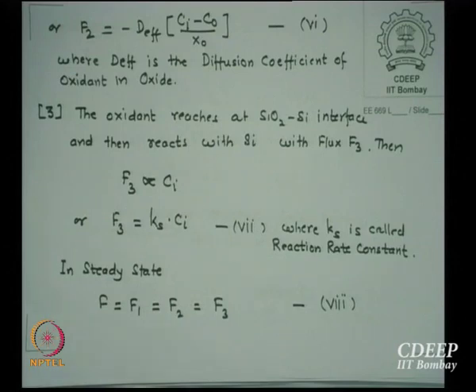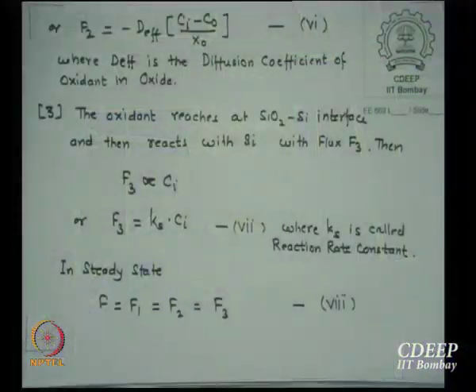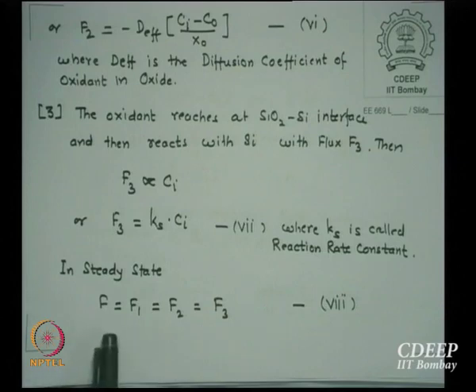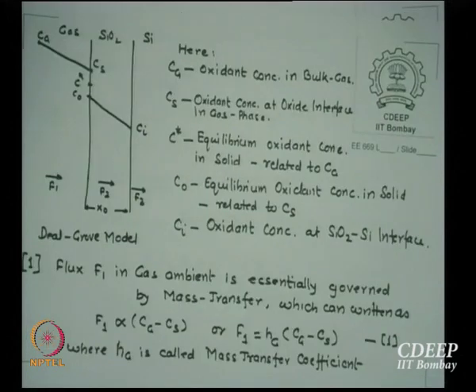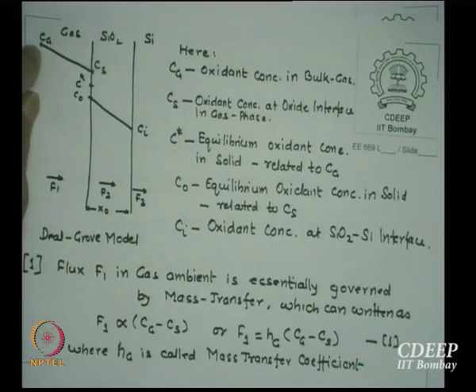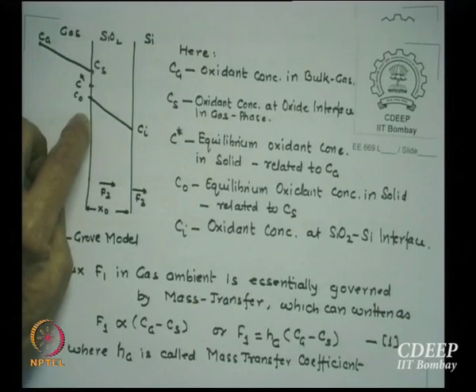F1 is from gas phase to the silicon dioxide surface. From silicon dioxide surface to silicon surface it diffuses and then reacts with silicon to form fresh oxide. And as I say, if I assume it's in steady state, which will happen, I put the wafer in a constant temperature, constant flow, the system will go into steady state. In that case, the flux F is F1 equal to F2 equal to F3. What we are saying, available concentration in the solid phase from the bulk is C star, of which only C0 is really going to diffuse because that is at the surface.